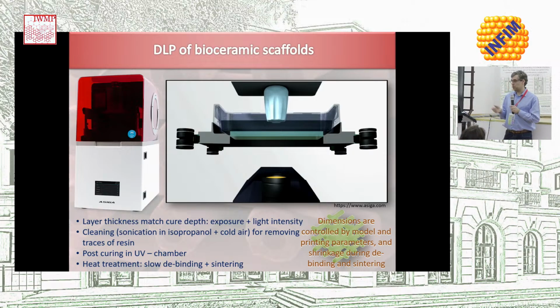Afterwards, you sometimes use some post-UV curing in a UV chamber. And then, if your material is not the polymer itself, but you want to produce ceramic, as typically in our case, you need to do a heat treatment later on to remove the resin, the photopolymer. We call that the de-binding process, which has to be very slow to avoid any cracking. And then you elevate the temperature to the sintering temperature for those powders that you are using. And the final dimensions of your material will be controlled by the model that you use, the printing parameters that you are selecting, and also by the shrinkage occurring during the de-binding and the sintering process.